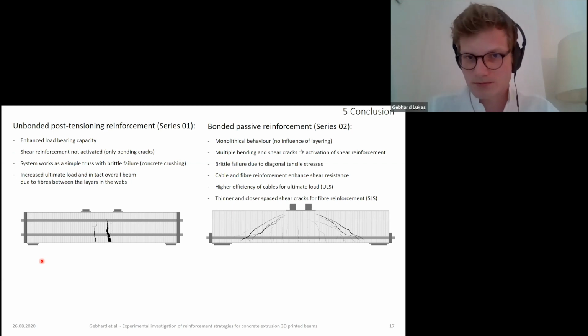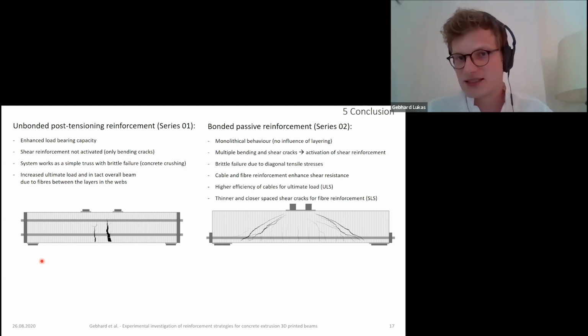For series 2, we could see that the behavior was quite what we would expect from monolithically produced beams, so the layering seemed to have really little influence on the overall structural behavior. We did develop multiple bending and shear cracks and could activate the shear reinforcement. All the beams failed again brittly in diagonal tension, which was, however, in this case intended since the bending reinforcement was quite over-dimensioned to provoke this shear failure. And both cable and fiber reinforcement enhanced the shear resistance significantly.